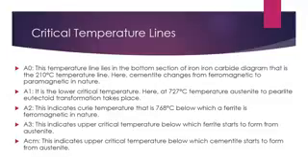The A1 temperature line is the lower critical temperature. Here, at 727 degrees Celsius, the austenite to pearlite eutectoid transformation takes place. The A2 temperature line indicates the Curie temperature, that is 768 degrees Celsius, below which alpha ferrite is ferromagnetic in nature. The A3 temperature line indicates the upper critical temperature, below which ferrite starts to form from austenite. The ACM temperature line indicates the upper critical temperature, below which cementite starts to form from austenite.